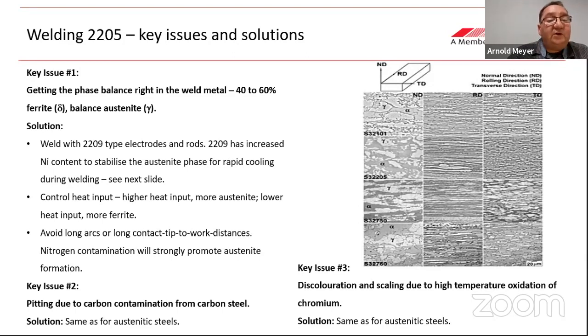You also need to control the heat input. The higher the heat input, the more austenite you will form. The lower the heat input, the more ferrite you will form in the weld metal. I'm talking about the weld metal specifically now. And then you need to avoid long arcs or long contact tip to work distances, because if you get any nitrogen contamination from the surrounding atmosphere, which usually is air, then you will strongly stabilize your austenite